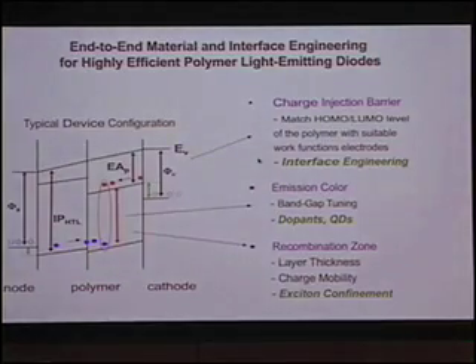So the same principle, charge injection and interface engineering, also applies, because this is a similar type of electronic device. In order to really build a very nice device, you need to have a relatively robust layer, because we focus on solution processing. In solution processing, the solvent you use for the top layer cannot dissolve or erode your bottom layer. So you need to create a very robust so-called hole transport layer, instead of just using vapor deposition, so you can do it layer by layer.